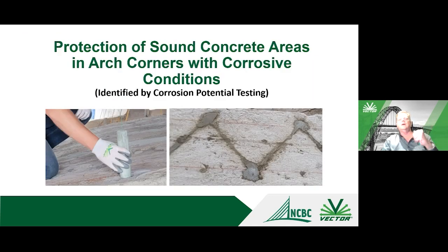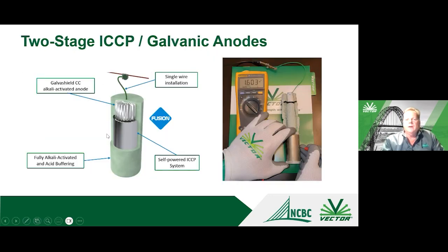And in this case, the consultant used a custom designed two-stage anode. Let me just go back one slide. And the way this works is it's two-stage. So the first stage is a self-powered ICCP system, effectively a battery that runs the first phase and that could be anywhere from a few months to a couple of years, depending on the design of the system. And during that period of time, you have a higher amount of current that's being generated than would have been by a galvanic anode. And then the idea is that you would passivate the active corrosion with this higher current in stage 1, and then when that occurs,